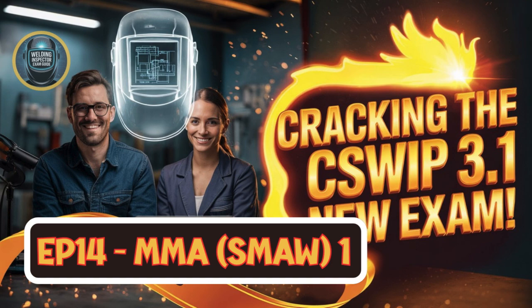You're constantly making micro adjustments to the arc length to match the electrode's burn-off rate. You're listening to the sound of the arc. A steady crackle or hiss is usually good. You're watching the weld pool, seeing how it flows, how the slag behaves, how it solidifies just behind the arc, all to create a weld that is structurally sound, free of defects, and has the right shape and size.